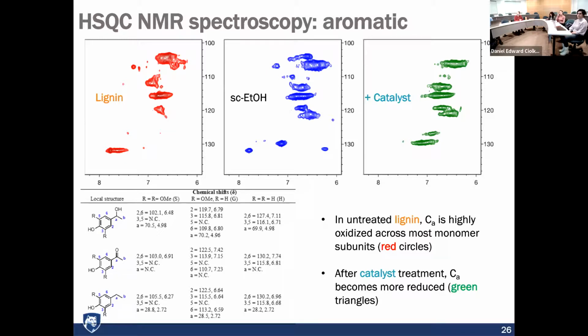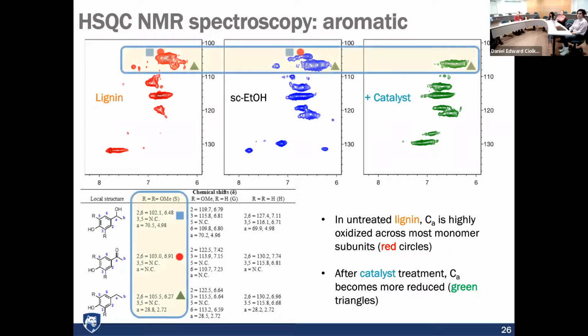So we're trying to monitor what's happening at this alpha carbon. And what we see is that here we have lignin that has not been catalytically treated, here it has been treated with just the solvent, and here with our catalyst. So lignin starts out with things that look primarily like this red circle. This big blob here is this red, which is why we picked our acetophenone monocompound. But after we do catalysis, most of the stuff that looks like the red circle goes away.